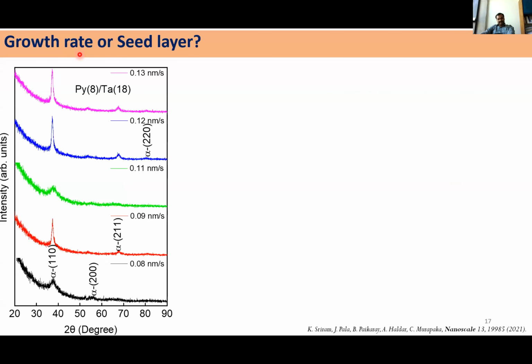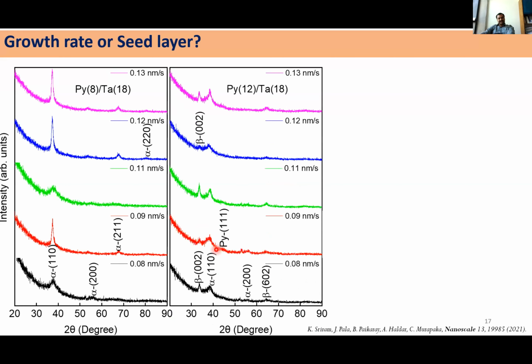And we wanted to see whether it is truly because of the growth rate or the seed layer, which one is effective. So what we have done is taken permalloy of 8 nanometer and deposited tantalum of 18 nanometer by varying the growth rate. You can see 0.08 nanometer per second to 0.13 nanometer per second, in all the cases when we deposited on permalloy 8, irrespective of the growth rate, we are getting pure alpha phase. The interesting thing is that when we take permalloy of 12 nanometer, even at 0.08 nanometers per second, where the reference sample shows pure alpha phase, here on permalloy 12, at different growth rates, we are seeing a mixed phase.